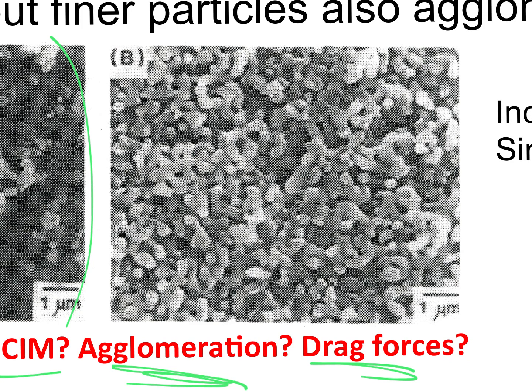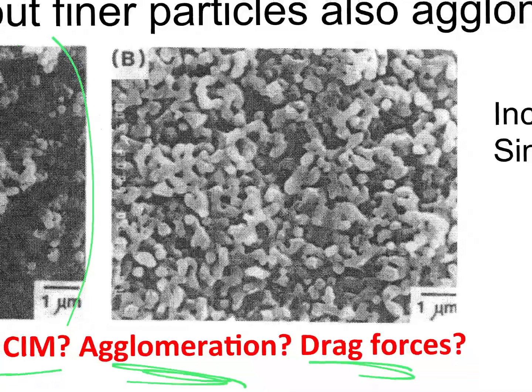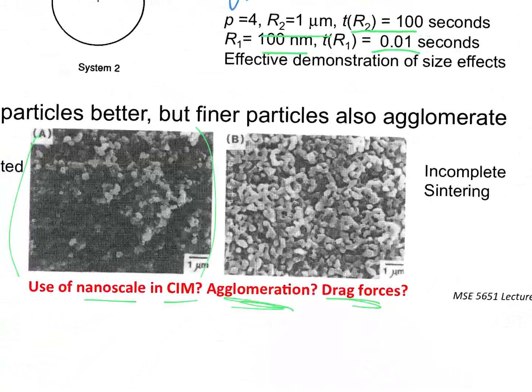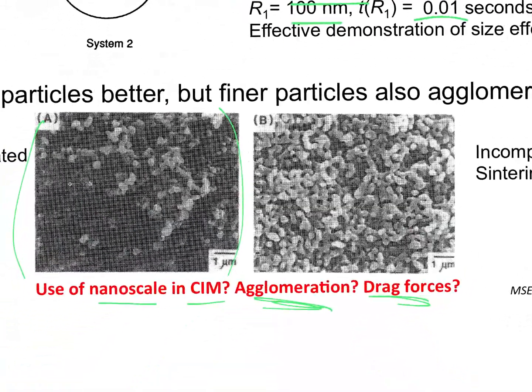All the particles are gone. They're all glued to each other. A lot of the porosity that was there is still there. So this is still a sponge-like structure, and the air will come out easily. But it won't take long for this to start sealing off those pathways and providing barriers to further densification in these systems. But we have to engineer the thing on the left-hand side, and then hopefully what happens on the right-hand side is more efficient because of how we engineered it.